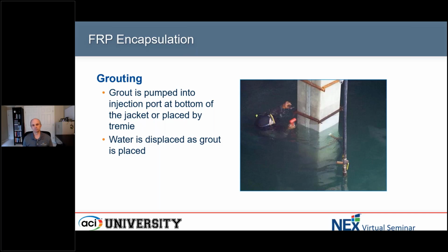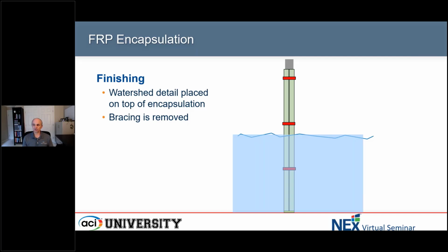You can monitor placement and make sure that things are being well consolidated, that voids are being filled, and that there's no large voids within that grout placement behind the FRP jacket. So it allows you to end up with a very good sound repair that is fully encapsulated behind that jacket. Then once the grout is fully placed, there's usually some type of watershed detail that's hand placed on the top of the encapsulation to make sure that any water doesn't pond on the top. And then the temporary bracing can be removed, and then the encapsulation is complete.